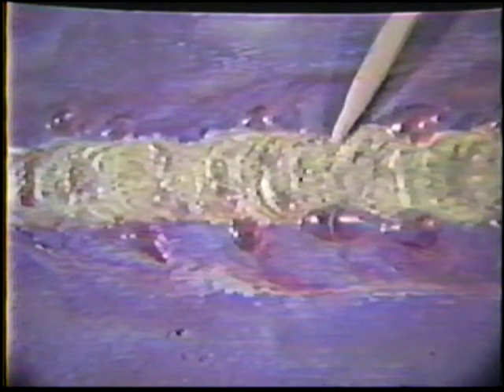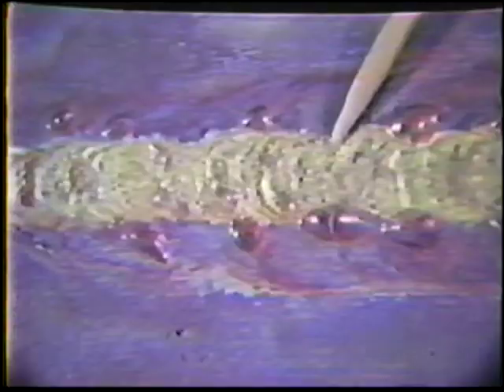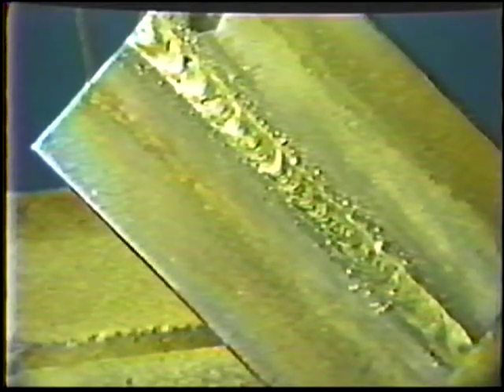Too much heat will produce a rough, discolored weld. A white powder of oxidized zinc will be present, and the braze weld may be excessively concave on the face and convex at the root. Too much oxygen will promote porosity and cause an uneven surface. A properly finished braze will be flat to slightly convex, bonding thoroughly with the joint edges with complete penetration to the root side. Inspect the braze weld and continue practice.